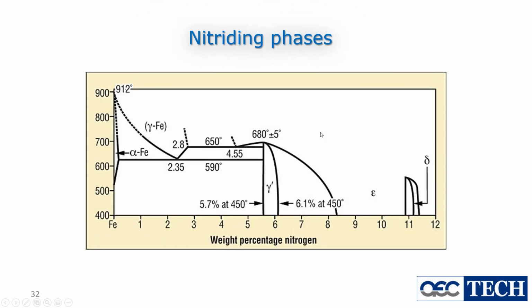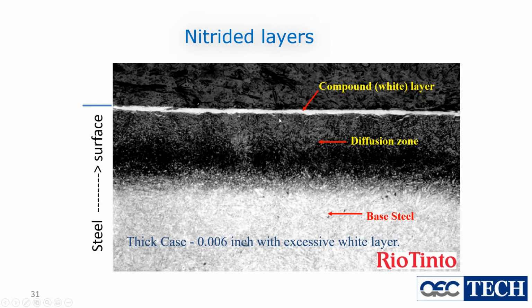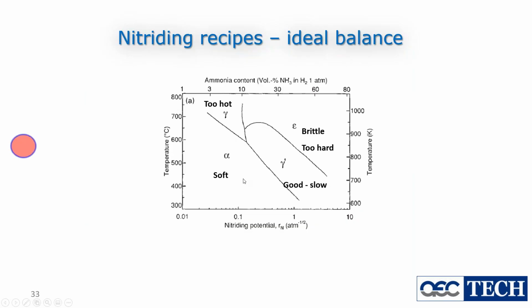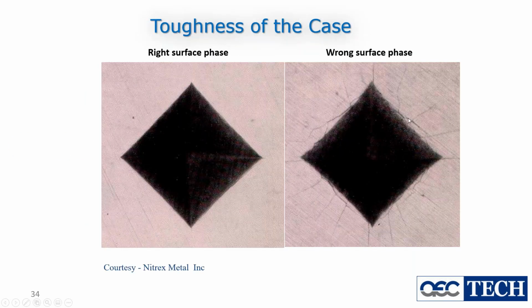No worries. If you look at those two and just look at the surface, you're going to see the same thing in both. If you just run the hardness test, you're going to get the same hardness. But if you magnify the hardness indenter more to see what's happening around it, that's where you notice that if you have epsilon, it's going to be brittle. You're going to have to see something like this to make sure that your nitriding is done properly. This is not good.